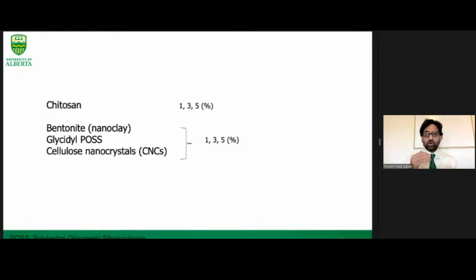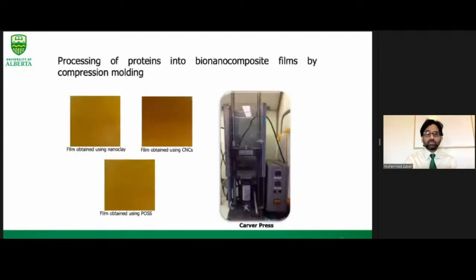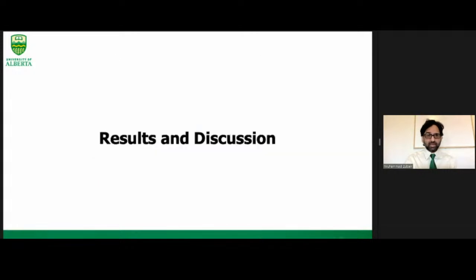After the addition of all these contents into the proteins, the mixture was processed using a Carver press to develop the films using compression molding at a temperature between 120 to 130 degrees. These are the films that we obtained using bentonite, that is nanoclay, and cellulose nanocrystals. And the third one is the POSS-based protein films. After the synthesis of these films, they were characterized and the protein purity was analyzed.